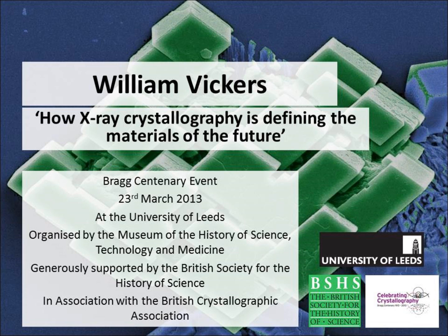So Tim Cumming and his colleagues looked to X-ray diffraction to try and explain why this was happening. And if they could explain it, they could improve the process and make it more efficient. They used the Diamond synchrotron source to take inline measurements of the particles while they were exposed to carbon dioxide and see what was happening to them. They were also interested in looking at an alternative to calcium oxide, and so they looked at calcium hydroxide.